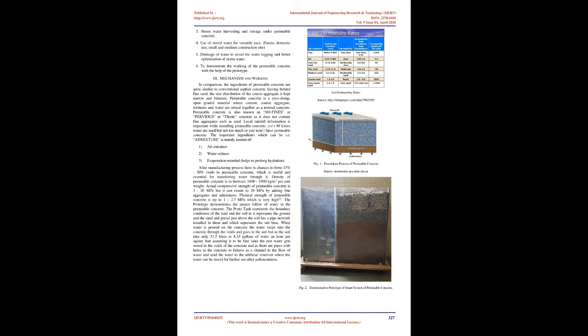3. Mechanism and working. In comparison, the ingredients of permeable concrete are quite similar to conventional concrete, leaving behind fine sand. The size distribution of the coarse aggregate is kept narrow. Permeable concrete is a zero slump, open graded material where cement, coarse aggregate, admixtures and water are mixed together as in normal concrete. Permeable concrete is also known as no fines, pervious or thirsty concrete, as it does not contain fine aggregates such as sand.